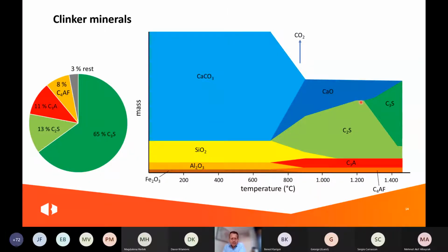Now here you can find the figure of producing modern Portland cement, but you also will find the steps in the past. Here you have the limestone, and in modern cement we have a part of clay. But of course this happened in the past, producing lime mortars. And later on with the hydraulic lime, when clay was added and a higher burning temperature, we were able to produce this component, the C2S, the belite. And in modern Portland cement, we go a bit higher in temperature, and we are able to produce the main component of modern Portland cement, and that is C3S, the alite.